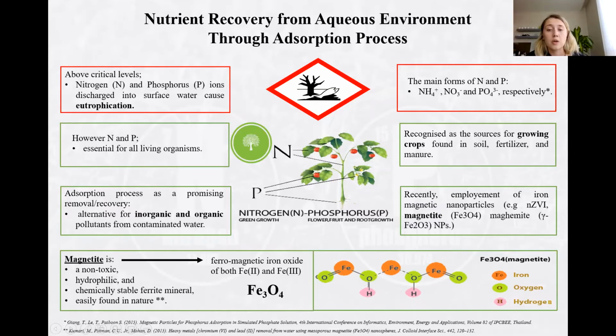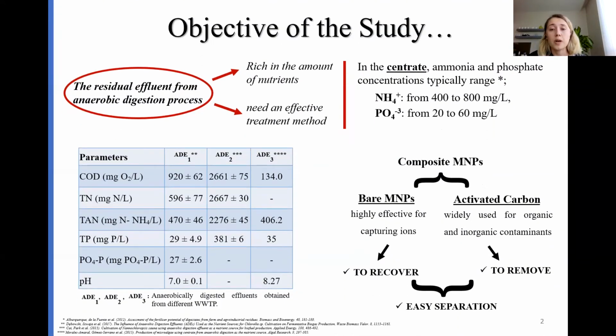Magnetite is one of the derivatives of magnetic nanoparticles, hosting various ions and molecules, and having great functional properties such as surface area, magnetism, etc. The objective of this study came out of the idea behind the adsorption of ammonium and phosphate ions by providing their recovery from anaerobically digested effluents. As you see in the table that shows the characteristics of various digestate effluents from different researches, these nutrients are rich in amounts. Therefore, we considered that evaluating the adsorption of these nutrients could be effective in terms of both the removal of organic and inorganic contaminants with the help of activated carbon in the composite magnetic nanoparticle form, and recovery of the ions by employing magnetic nanoparticles in bare form.